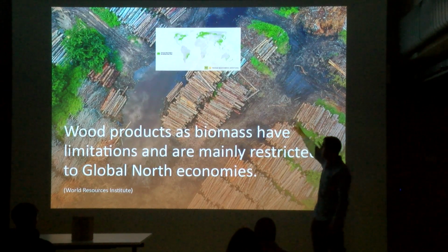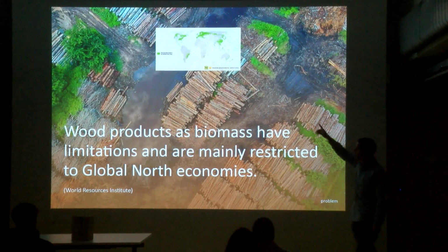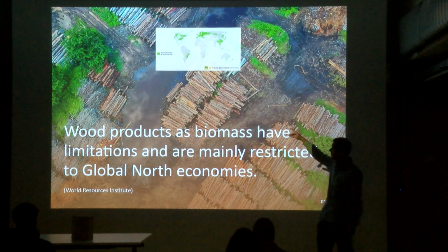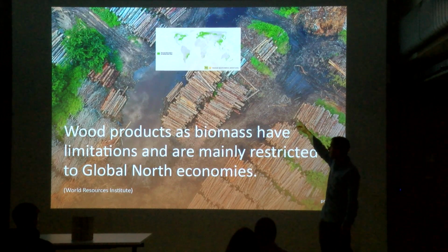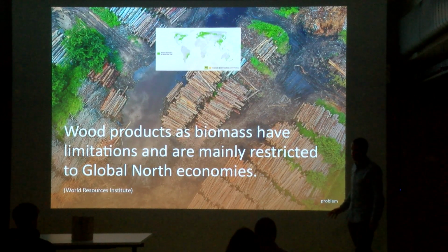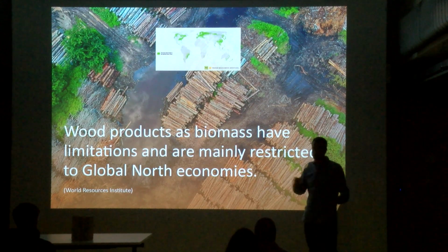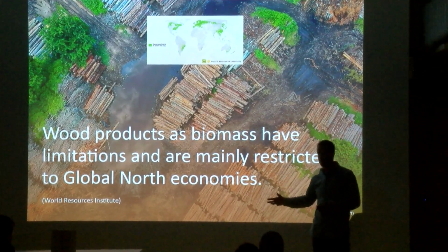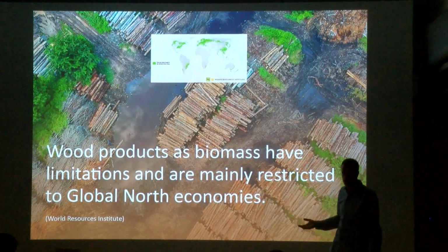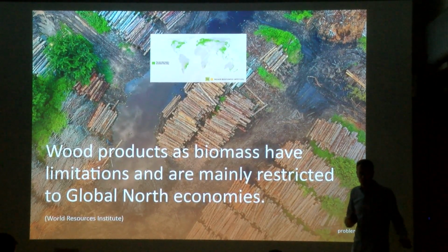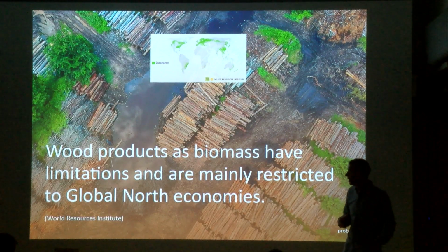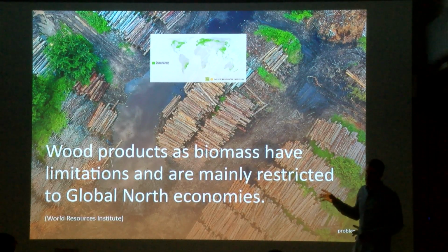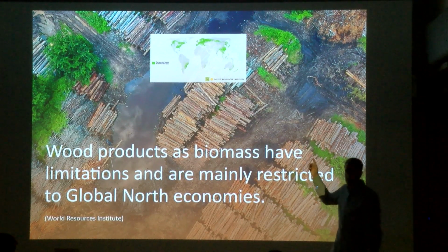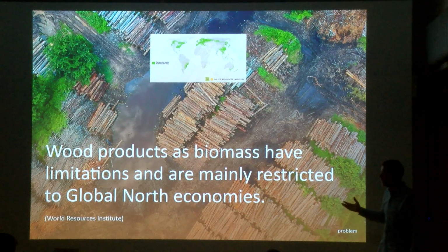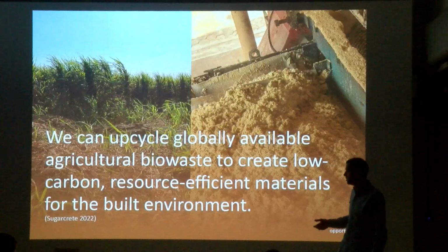And if you look at that map from the World Resource Institute, all the areas in the global south, most of Latin America, Africa, and most of Asia, including India, there is no timber industry. There are no factories that are producing cross-laminated timber, and timber is just not available for construction, which means that they are left with alternatives such as brick, concrete blocks, concrete, many times imported material, high carbon materials, and almost 50% of the global built area that is going to double by 2050 is going to happen in these areas. So we thought that it was key to address this issue with different and alternative materials.